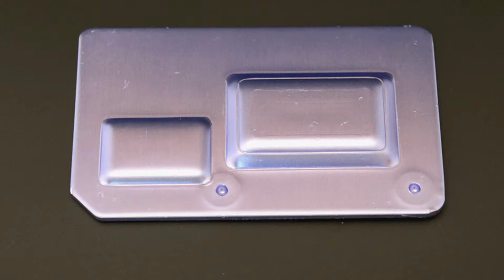That color is actually dependent on the alloy series and your pretreatment. Sometimes it's a little stronger, sometimes it's more of a brownish, purplish, bluish. It could have a blue hue. You can reduce your immersion time for certain alloy series where you don't want to see as much color. It shows up very well on the lighter alloys like 2024, those that have a lot of copper or zinc in them, so it has a variation. But violet would be from the rainbow if you're going to go that way.